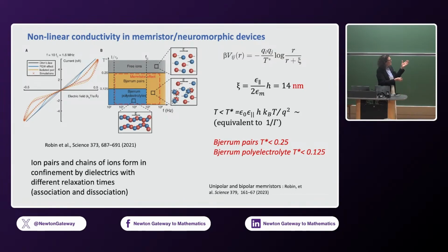And so, he has very beautiful theories about the interaction when you have a strong confinement. If you remember your classes of image charge, when you're pushing charges, the image charge, in a low dielectric, is of the same sign. So they are interacting very strongly, almost logarithmic, like if it was 2D. And they depend on this parameter that in water can be significant because in confined water, the dielectric constant is not anymore 80, but it's much more reduced. It can be actually 7 or 5, okay?